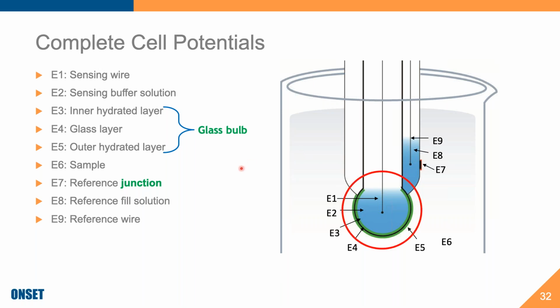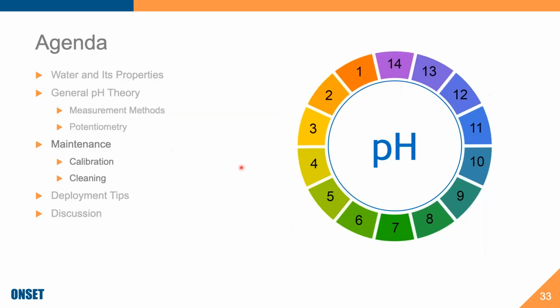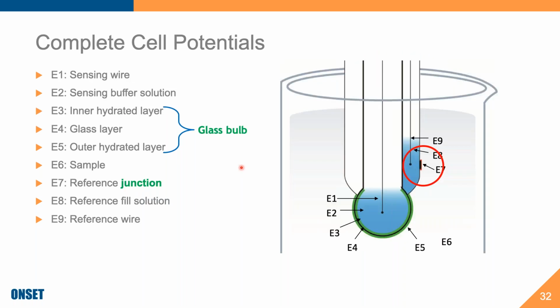So here's our glass bulb. It has 5 different potentials. Then the junction has 1, 2, 3 in terms of how it relates to the reference. Sorry about that. So if you're going to take one thing from this slide in terms of best practices, I would strongly suggest that you remember that the glass bulb isn't just meant to be cleaned, but it needs to be hydrated and conditioned, and we'll cover this again. And the reference junction as well, same thing. You don't want a dry reference, especially if it's a ceramic, and you also don't want a dirty one.